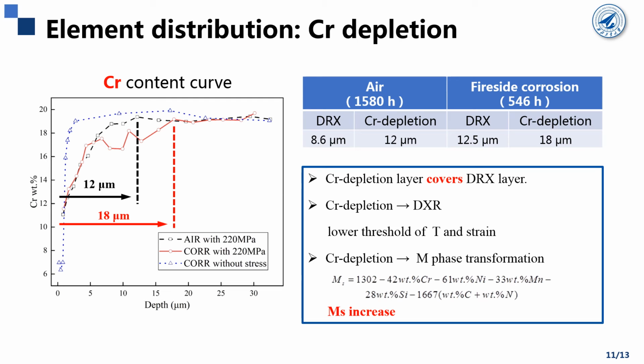On the other hand, it has also been reported that martensitic phase transformation is also favored by the surface chromium depletion, because the martensitic phase transformation temperature point, termed the MS temperature point, can be increased by the decrease in chromium concentration in the alloy. So these facilitate the occurrence of martensitic phase transformation during the cooling process to room temperature.